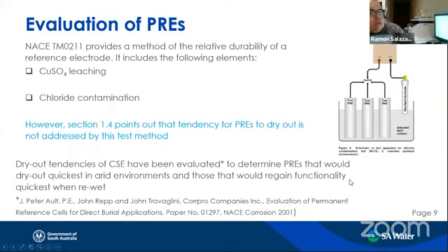Now, in terms of evaluation of reference electrodes, in NACE we have TM0211, and they provide a method to evaluate the durability of reference electrodes. However, what they measure is the copper sulfate leaching out of the reference electrode or chloride contamination. They say in section 1.4 that they are not measuring the tendency to dry out, so it's not addressed by this test method.